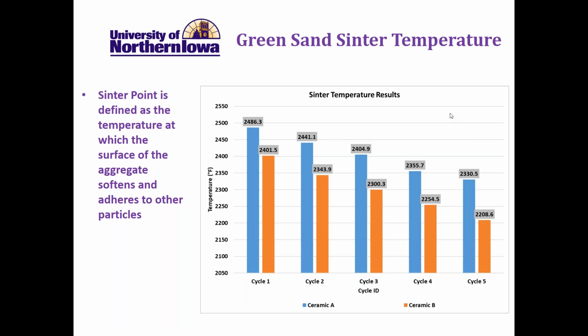We did this because then we proceeded to make cores, phenolic urethane cold box cores, out of that reclaimed sand, and then use the balance of the reclaimed sand plus the cores for our green sand dilution. This was a closed loop system. So every bit of sand that was used in cycle 1 was also used in cycle 5.